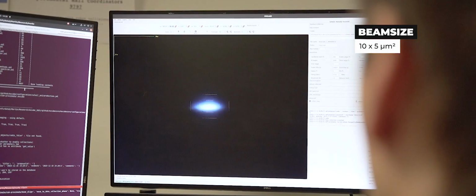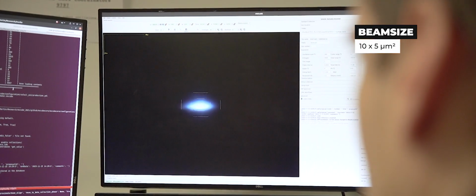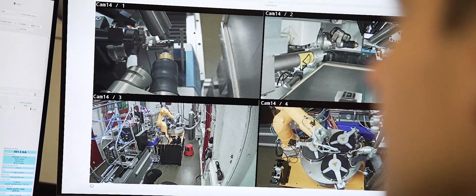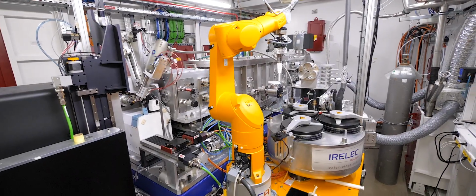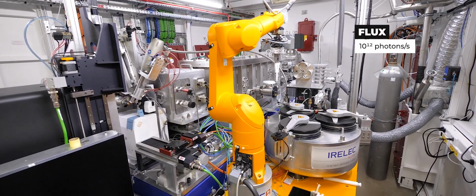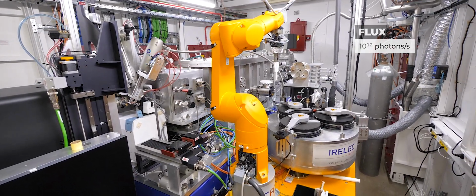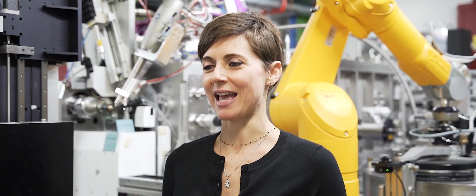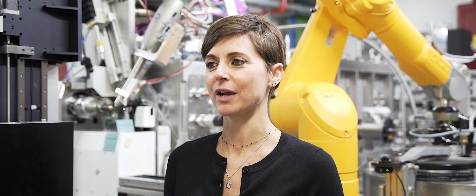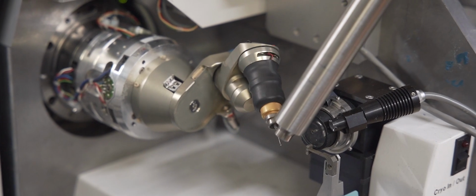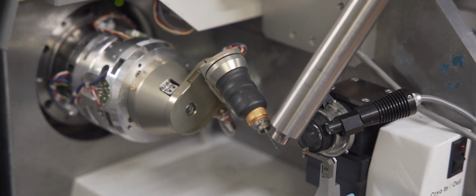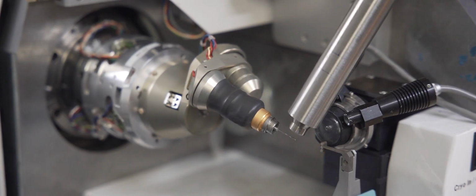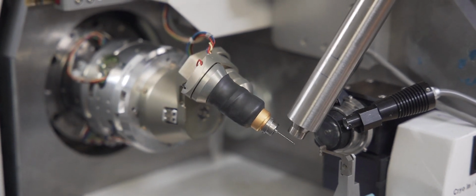The beam is focused down to 10 times 5 microns by a pair of adaptive X-ray mirrors. Together, the source and optics deliver an X-ray flux in excess of 10^12 photons per second. The Proxima IIa end station is optimized for microcrystallography experiments and consists of a multi-axis goniometer, a large sample changer robot, a cryostream, and a large fast X-ray area detector.